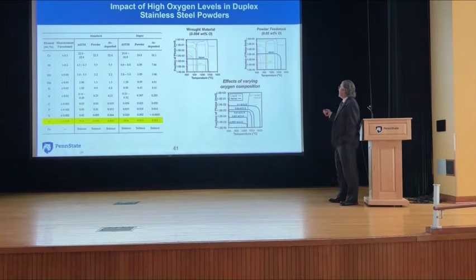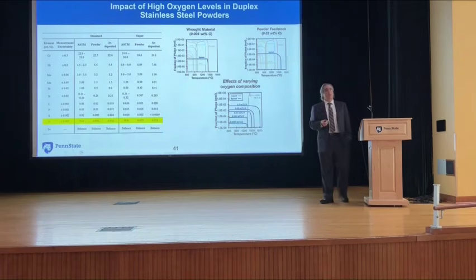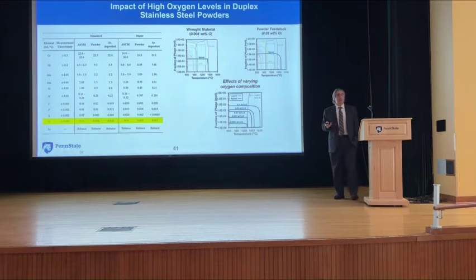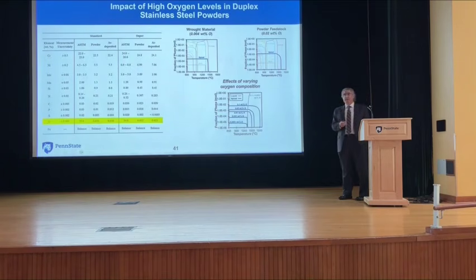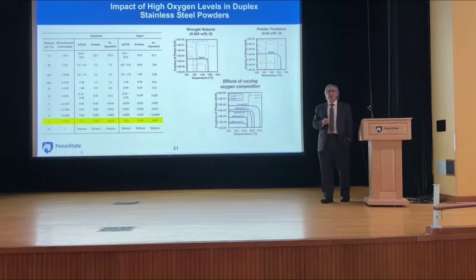Now, when I take it into powder, I increase the oxygen content just a little bit, from 0.02 to 0.04. I mean, really, what's 1/100th of a weight percent among friends? It's not very much, right? Unless it's a gas. What I start seeing is this spinel phase, which is a chromium manganese oxide, starts to form in the liquid, which means, can I heat treat my way out of this? No, it's there forever. So until you do something else.